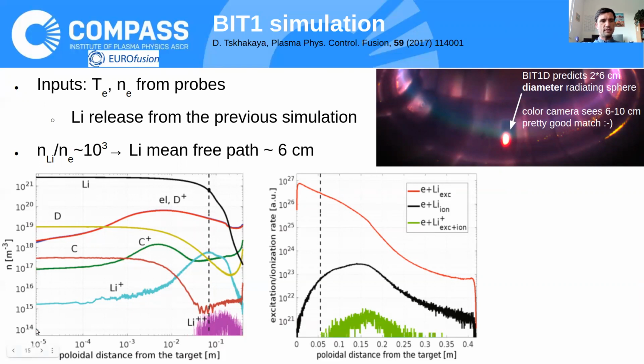So this is the density in cubic meters in logarithmic scale, and this is the distance from the target in logarithmic scale. You can see that near the target there is only lithium, and then it starts to decrease at about 6 centimeters away from the target. Close to the target, it is 3 orders of magnitude larger than the density of deuterium plus. And there are also some neutrals of deuterium. And we included also carbon, lithium plus and double ionized lithium.